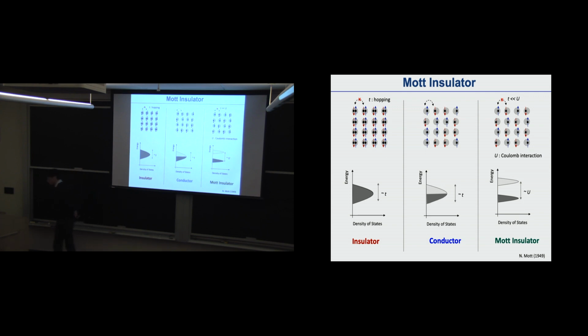Of course, this Mott picture itself does not tell us what the spin structure is at these sites. Now, if you consider the residual exchange interaction between electrons at the sites, depending on this exchange energy scale, you can get different spin structures. Often in a Mott insulator with short-range interactions, the spins tend to anti-align, such that most Mott insulators we know are antiferromagnetic.